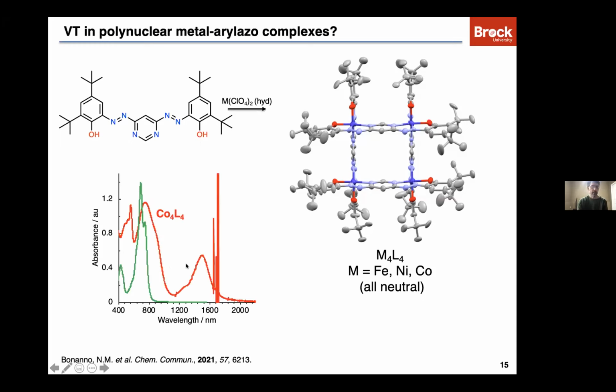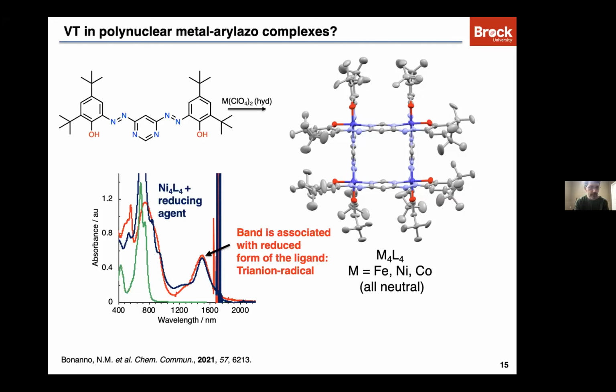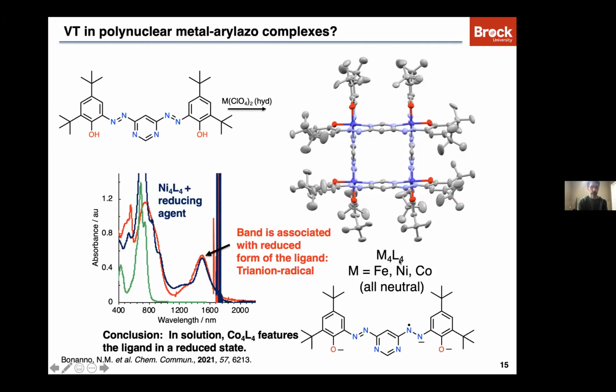But with the cobalt complex, there's something completely different. The cobalt complex, we have this very, very low energy band in the near IR and a very different electronic structure. In fact, if we take the nickel complex, which is this green spectrum, and we reduce it with some reducing agent like sodium metal or something, we see a band grow in the same region that we see with the cobalt complex. So that band is associated with the reduced form of the ligand, which is a trianion radical. So this is the form of the ligand that we have in the cobalt complex that we produce simply by reacting the ligand with cobalt perchlorate.